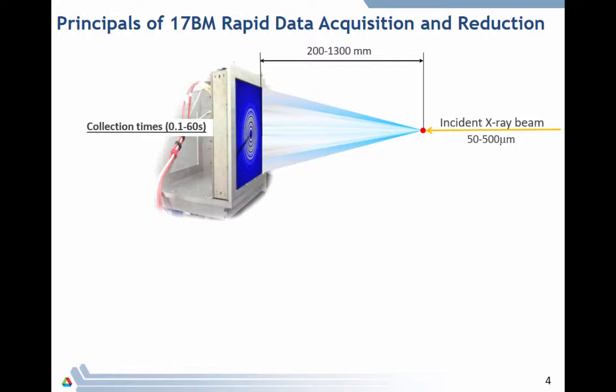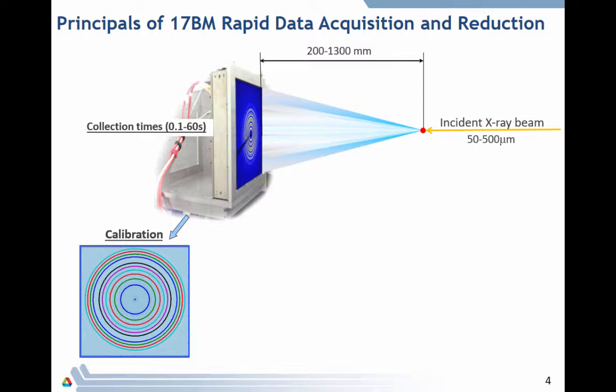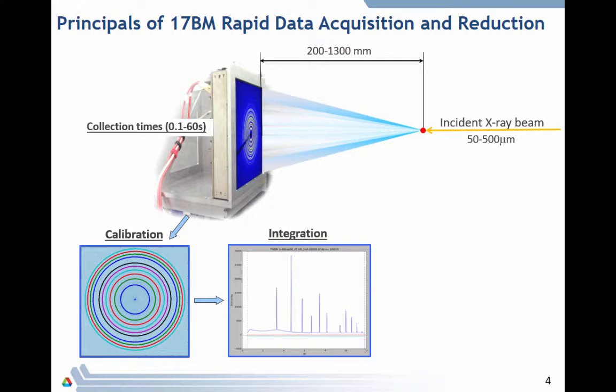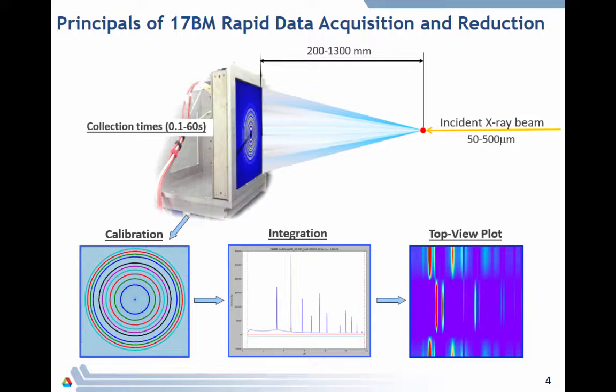When we receive the image on our detector, we receive 2D powder data. After that, we calibrate the image by introducing calibration parameters such as the sample to detector distance, tilt of the detector, and so on. After that, we integrate the data and receive actual 1D powder data. But again, we are a rapid acquisition powder diffraction line, so we are collecting a lot of powder diffraction data, and we very rarely analyze just a single pattern. We usually collect a lot of them and stack them up, producing a so-called top view plot or contour view plot, where we can easily see any structural changes in the material and what's going on during your particular experiment.